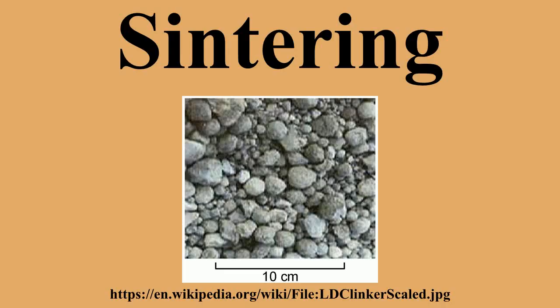Solution precipitation. In areas where capillary pressures are high, atoms will preferentially go into solution and then precipitate in areas of lower chemical potential where particles are not close or in contact. This is called contact flattening. This densifies the system in a way similar to grain boundary diffusion in solid-state sintering. Ostwald ripening will also occur, where smaller particles will go into solution preferentially and precipitate on larger particles, leading to densification. Final densification. Densification of solid skeletal network, liquid movement from efficiently packed regions into pores.